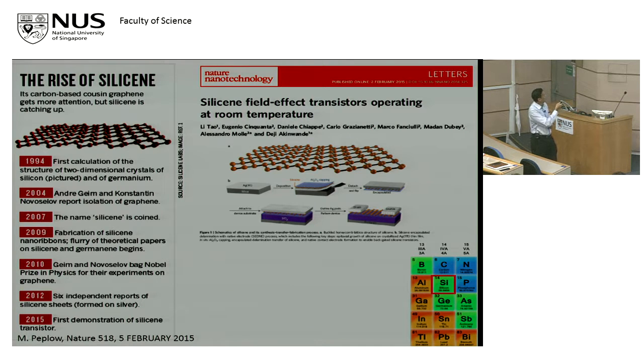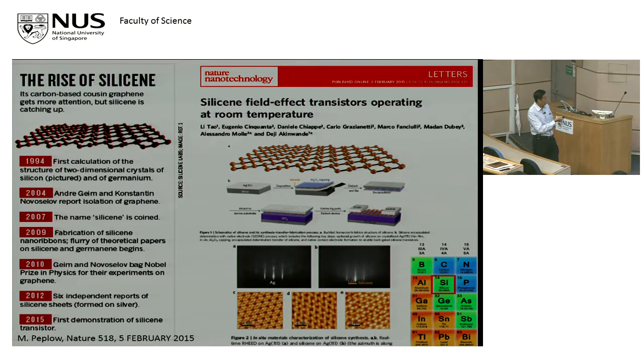So what you see in 2D is, first of all, not quite flat. Secondly, it's always on a substrate. So they grow it on silver. If you look at the STM images, this is silver 111. It's grown on silver, okay? But it means you can't make it stand alone. So obviously the silver does alter the properties a bit. But nevertheless, these people made a device and they published in a high impact journal because they demonstrated a silicene transistor. But it is still a great challenge to make real silicene that's isolated, having the theoretical properties that it promises. So this is a subfield that some people are working on.